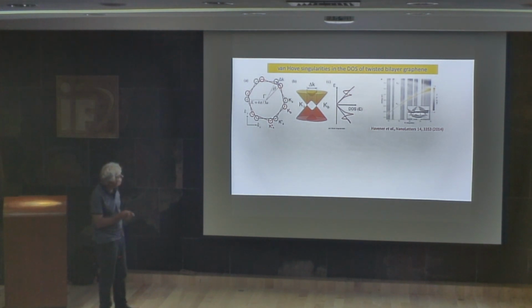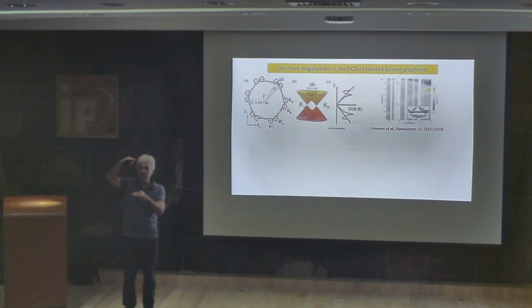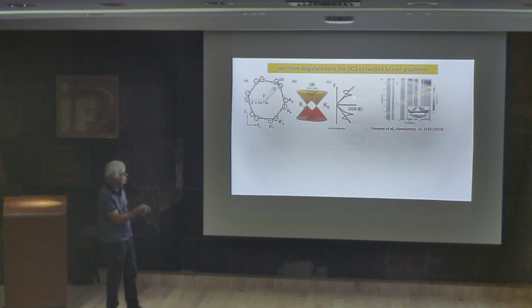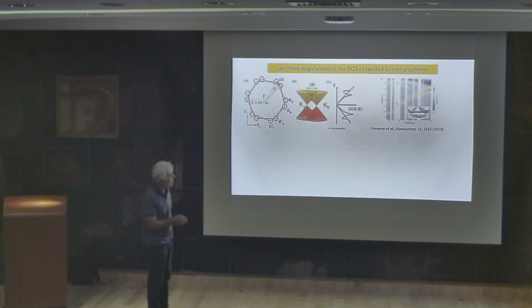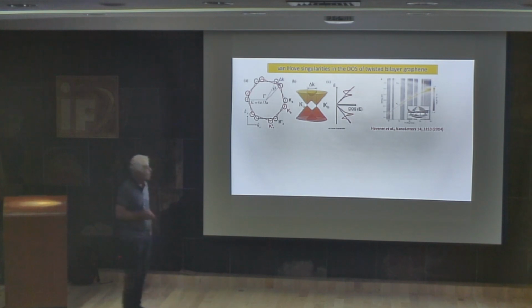You can see that the distance between those Van Hove singularities is proportional to the twisting angle. Then I can tune the position of those peaks by just changing the angle between those two layers. And it was realized in this paper in 2014 that we can have optical transitions between those peaks.